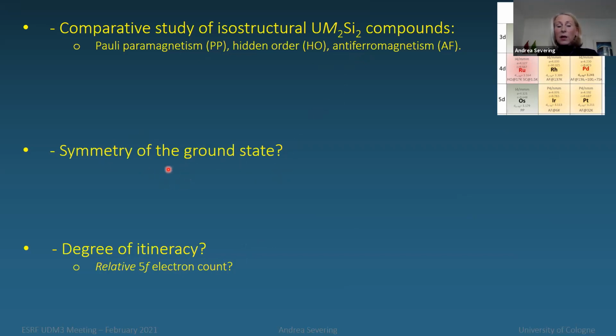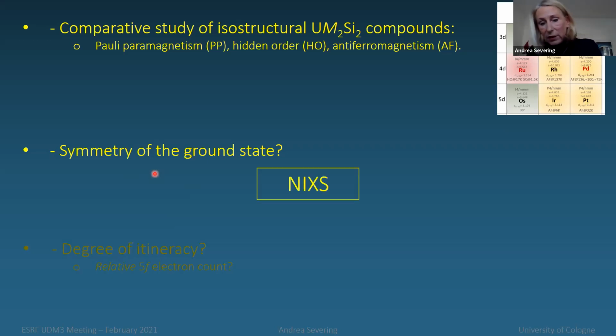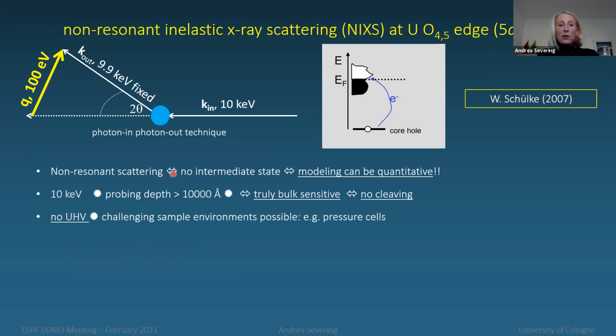And also, I think Sergei Butorin will talk more about this, the fingerprints in your spectroscopic data, the spectra, depend on the ground state symmetry. So if you really want to compare and get a relative f electron count, we have to make sure our compounds have the same ground state symmetry. And that we are investigating with NIXS. This is non-resonant inelastic X-ray scattering.